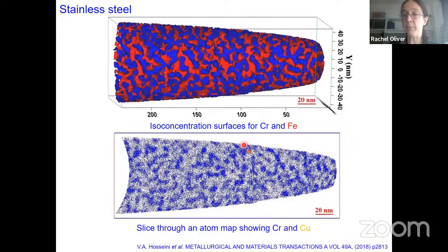So this is an example of that from metallurgy. This is a stainless steel sample. And what we've got here is a sample with iron, chromium, copper in it. And we're showing up here in red regions that are essentially iron rich and regions that are chromium rich. And we've also got a tiny splodge there of copper rich material. And this allows us to look at these kind of nanometer scale variations in composition in metals.